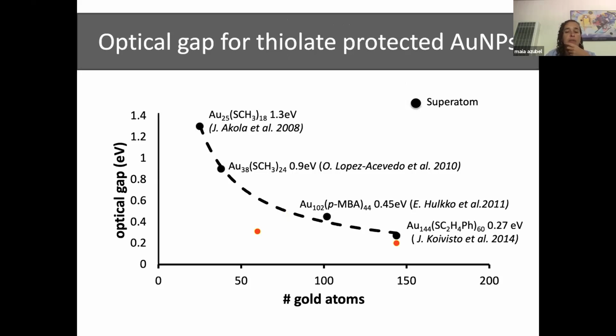So one brief comment is that by the time I solved the structure, there was a lot that had been mentioned about the optical gap of the clusters, that most of them were superatoms. There was a clear tendency, and my two clusters fall off that curve, which means that for the same size, they were much better conductors than predicted. And again, this has to do with the lack of symmetry. And that's something that you can see in Häkkinen's paper. When you have lack of symmetry, the molecular orbitals relax. So the gap that you have between the HOMO and the LUMO is smaller.